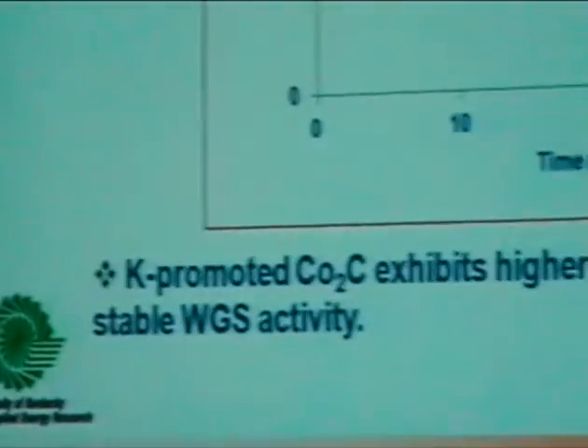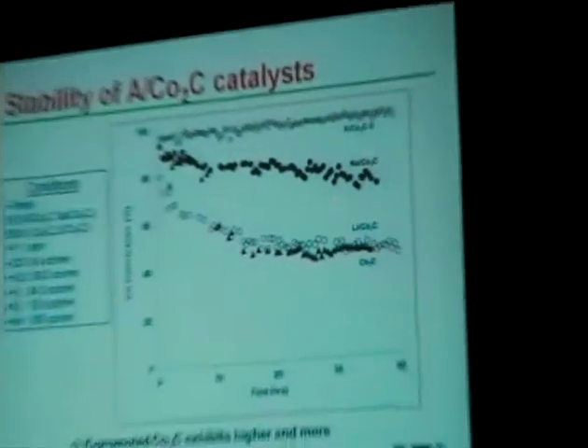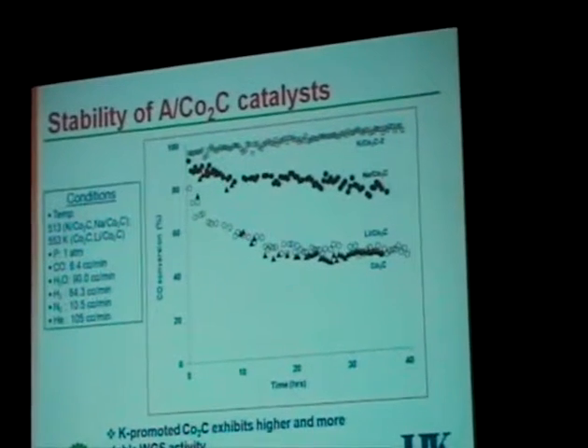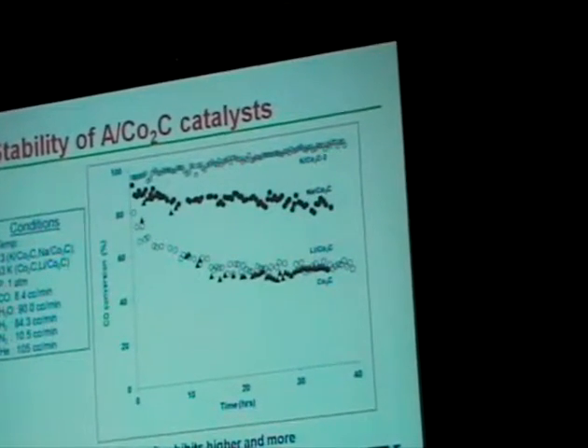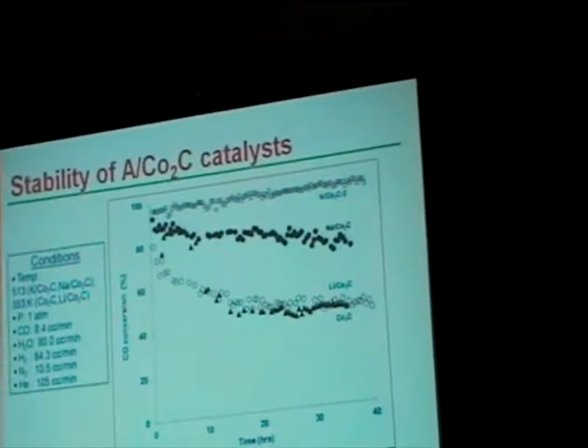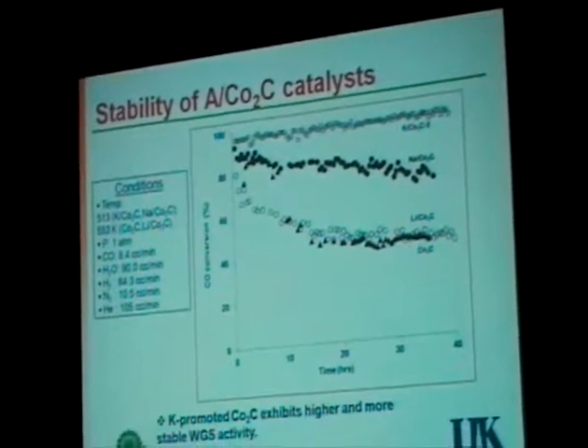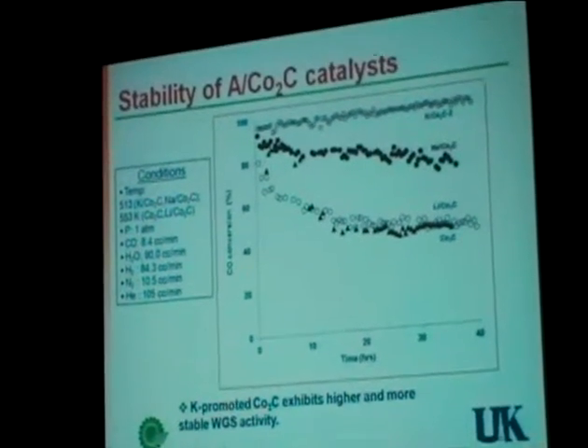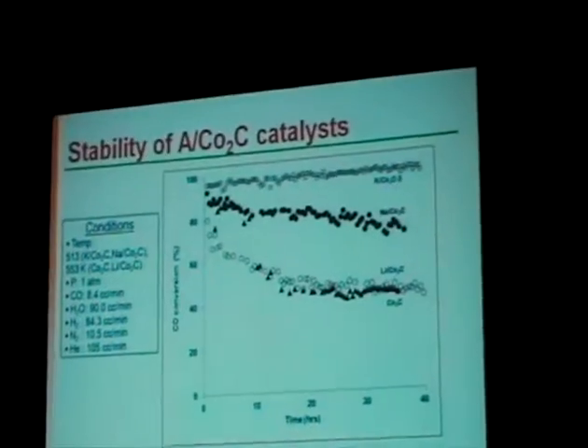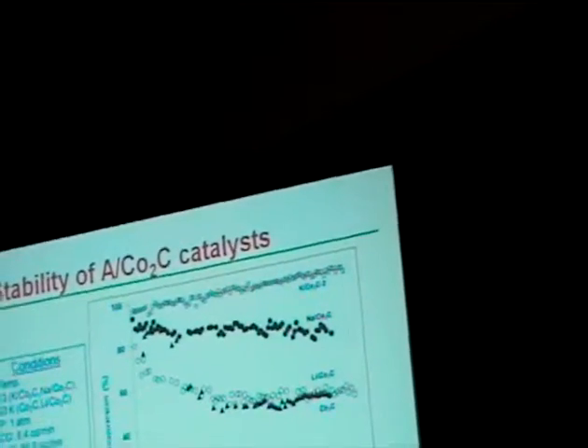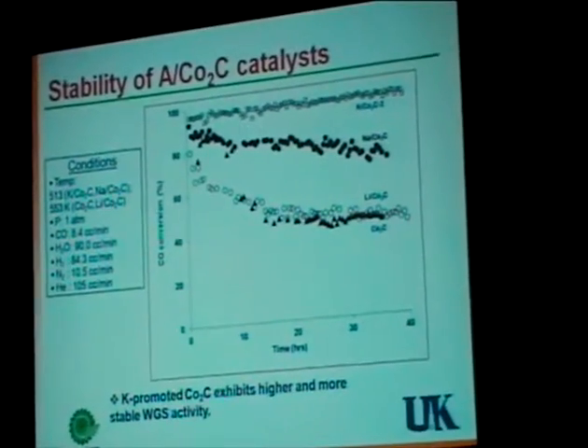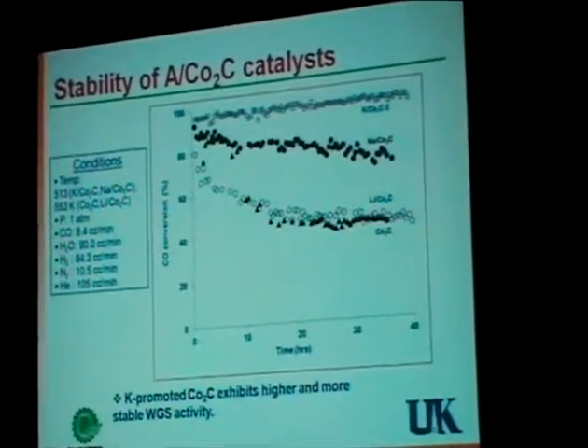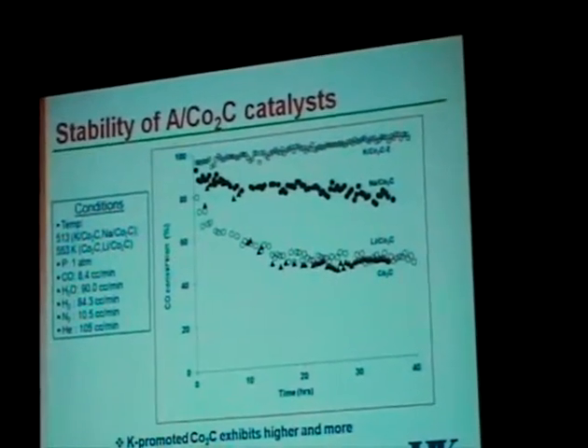And finally, we are comparing the long-term stability of the catalyst with the various alkali metals, and as you see, the water gas shift activity dropped for cobalt, lithium, and sodium. Sodium also has shown some deactivation, but is really comparable with the potassium. Although the potassium has shown a higher activity, and it was quite stable for close to 40 to 50 hours of run. So potassium promoted exhibits higher and more stable water gas shift activity. Of course, we have seen this effect on rubidium as well as cesium, but I am not showing it here. But rubidium and cesium also show a similar deactivation behavior.